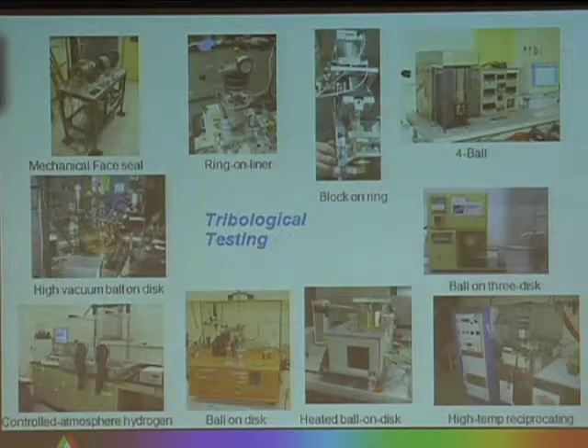Shown here are a number of different tribological testing capabilities. All of these are essentially lab-based. They're not actual components, but they're set up in such a way that you can utilize a very well-defined configuration, a ball on disk or a ring on disk. You have a point contact, a line contact, or an area contact. You can control the load that's applied, control the contact stresses.